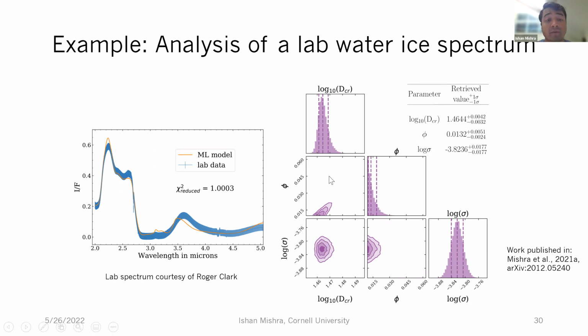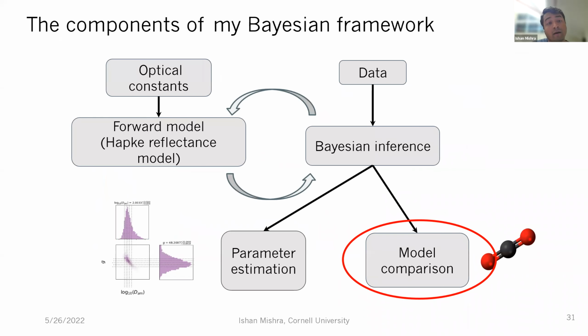And especially, our goal was to constrain the grain size, and we got a pretty good constraint, accounting for degeneracy with two other parameters. So this is porosity, and this is an uncertainty on the error of the data, because that was not well characterized. So we let that be a free parameter as well. And we got pretty good constraints, and the median value was also close to what was cataloged for the sample in terms of average grain size. So it's pretty decent. So now moving on to model comparison.